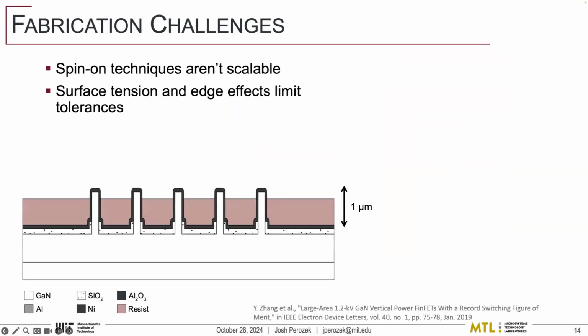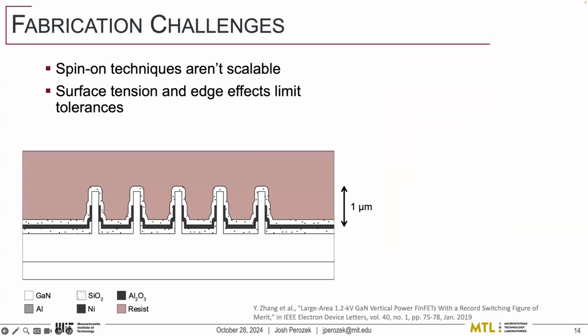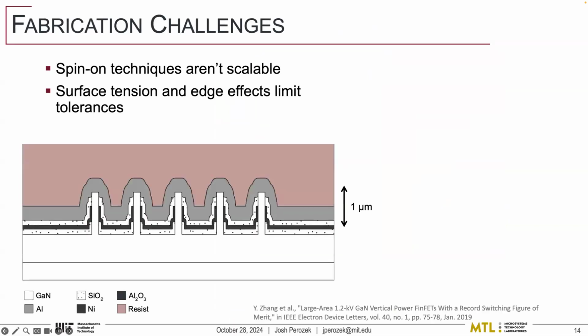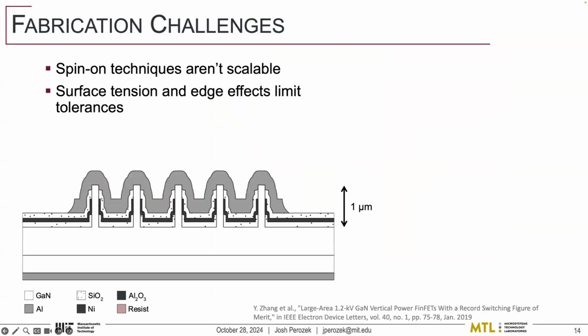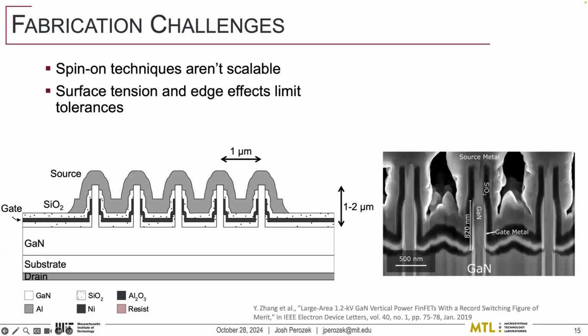The first ones we ever made used this process of build up: put on photoresist to planarize the surface, etch it back very carefully with an oxygen dry etch, and then whatever's exposed after you etch back the resist, you can etch with a different etchant. And when you're done with this, you can get a very nice FinFET cross-section over here. On the right is a cross-sectional SEM that we took in a FIB of these devices. And it's really great for one-off demonstrations.